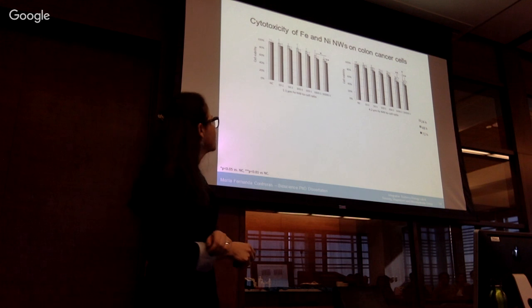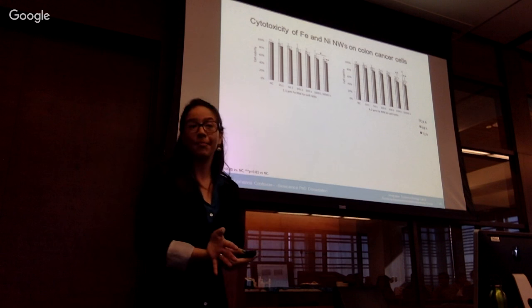Okay, so I will be first talking to you about the cytotoxicity or cell toxicity of iron and nickel wires on colon cancer cells. I always work with this type of cells. And I did these experiments with an MTS assay that measures the metabolic activity at the mitochondria. So these are the results for iron wires, 1 micron and 4 micron wires. The color codes for the incubation time of the wires with the cells. So we have these three time points here. This is cell viability, so how basically happy the cells are.